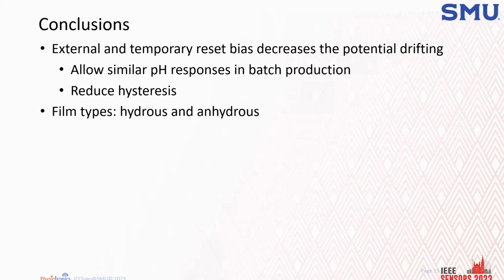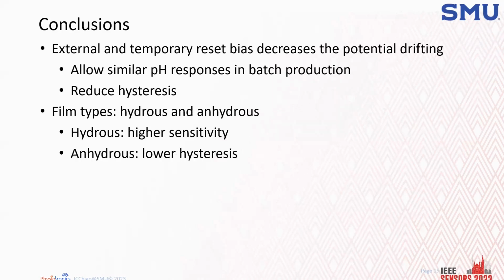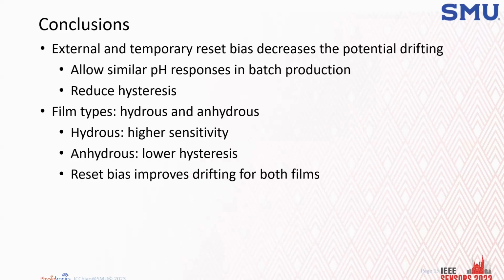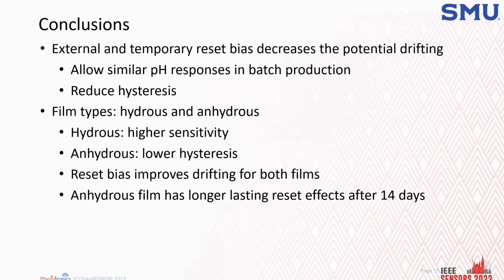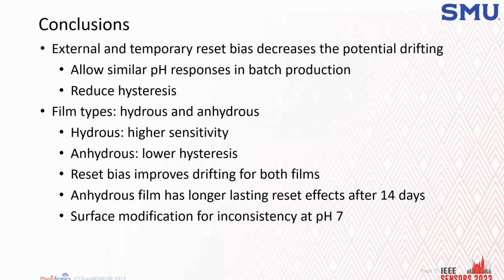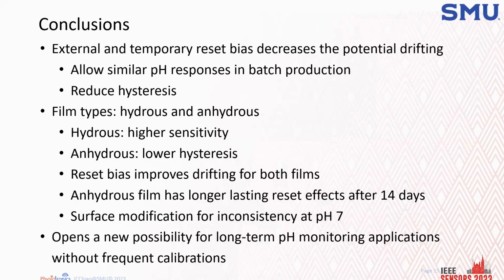Also, we tested 2 different types of film, hydrous versus anhydrous. We found the hydrous sensor has better sensitivity, but the anhydrous sensor has lower hysteresis. However, the reset bias improved both films, which means that we can use this reset bias approach for all pH sensors in the same application. We also found that the anhydrous film still has a long-lasting reset effect even after 14 days without using the electrode. And for the hydrous one, we found there's a surface modification at pH 7, which means that you do need to calibrate toward pH 7.